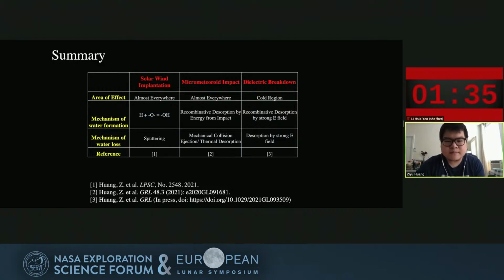The implantation and micrometeorite impacts are almost everywhere, but there are different conditions, like the solar wind velocity and implantation angle. Dielectric breakdown occurs mostly in colder regions. And currently, we can conclude that within PSRs, the combination of implantation and micrometeorite impact can continuously accumulate water molecules and garden them into a deeper depth. And there are some periodic features of the combination in the contribution to water molecules.